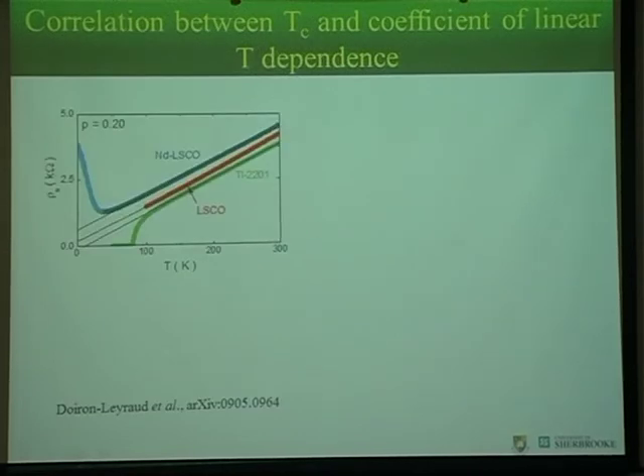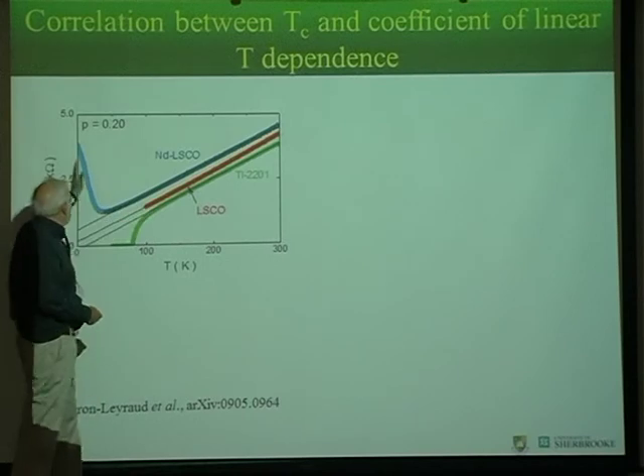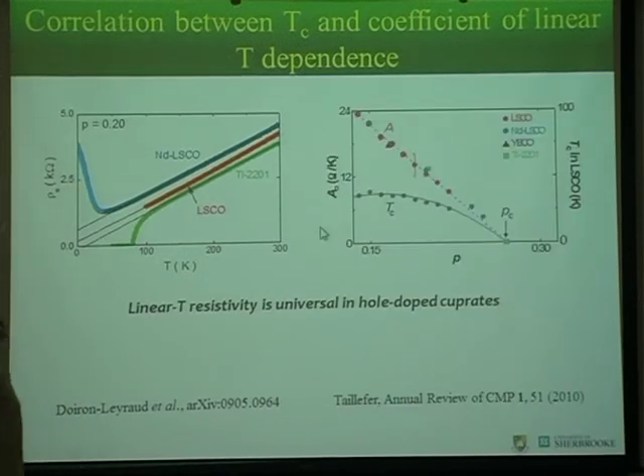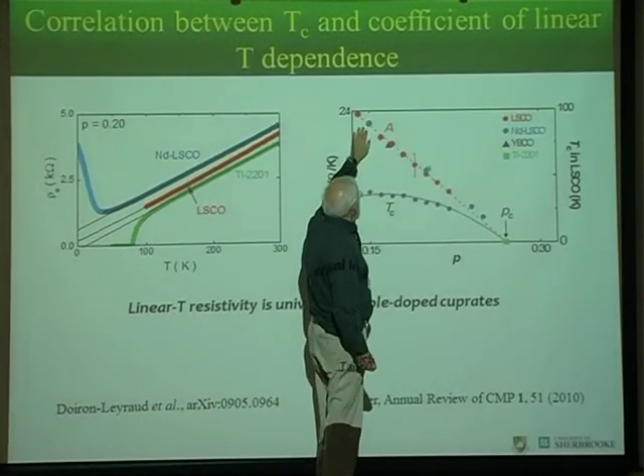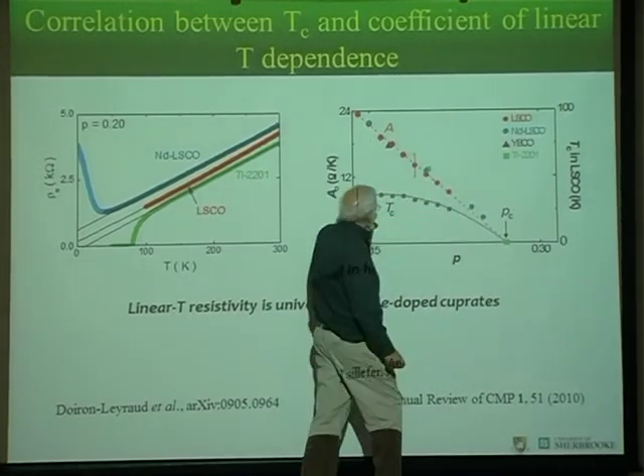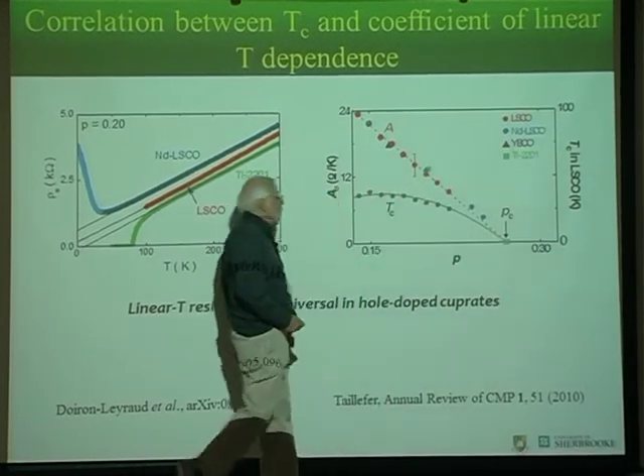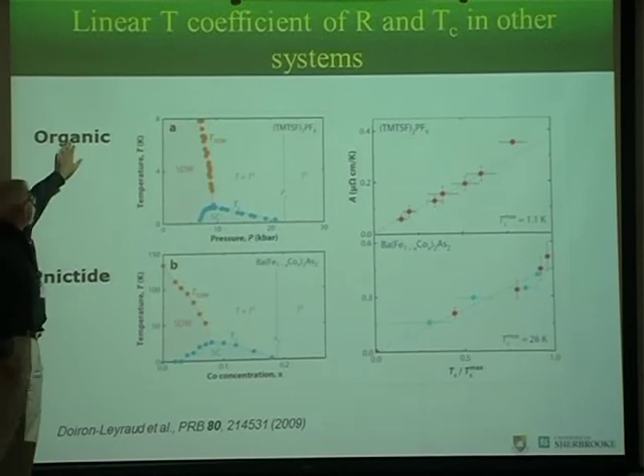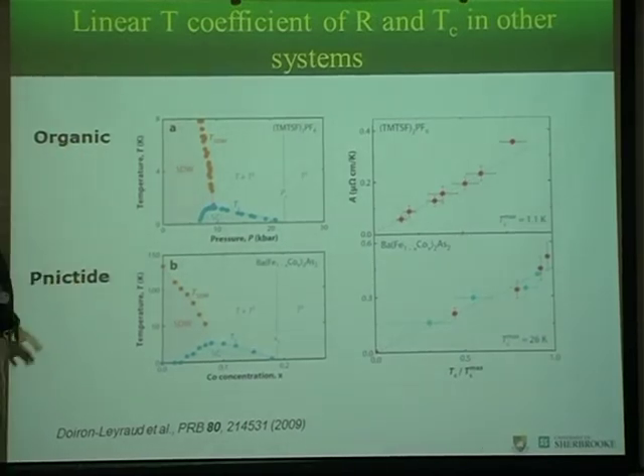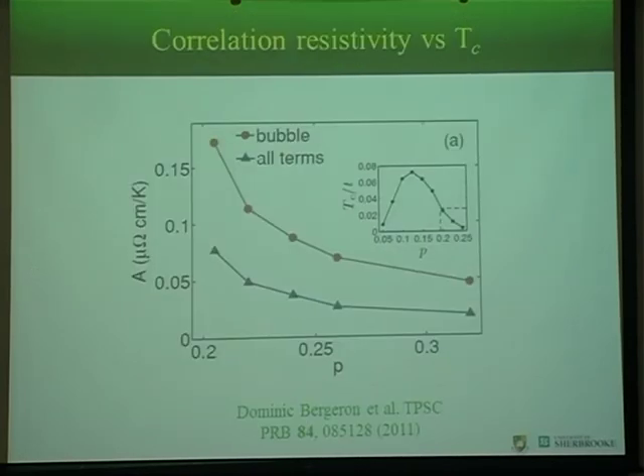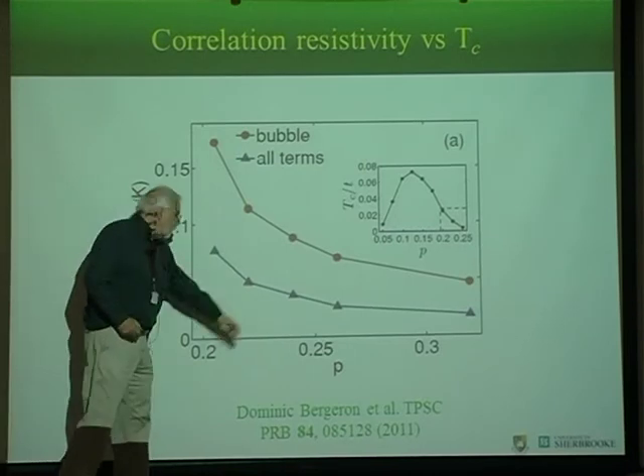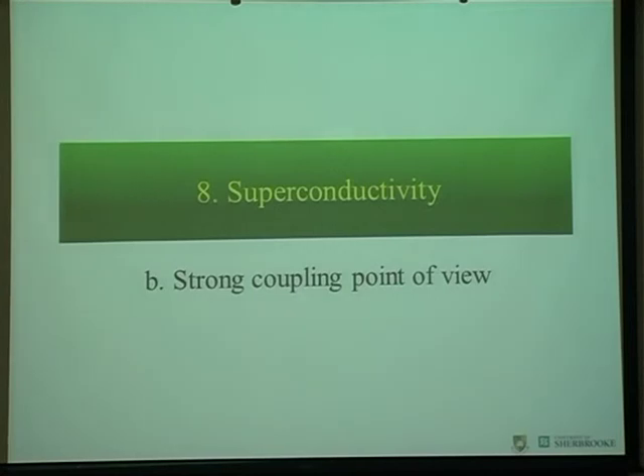Okay, now the other correlation that is seen experimentally is that the slope of this linear dependence, so you have some number times temperature for resistivity as a function of temperature. The value of this coefficient, the slope here, goes to 0 where Tc goes to 0 in the overdoped case. And this correlation has been seen also in the one-dimensional organics and in the pnictides. So this seems to be a strong correlation. In the two-particle self-consistent approach, we don't quite have that, but we do have a decrease of the linear coefficient.